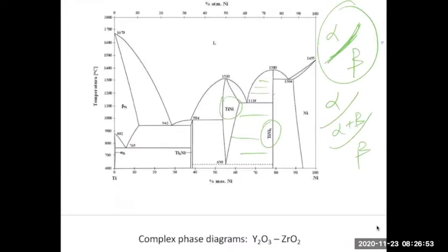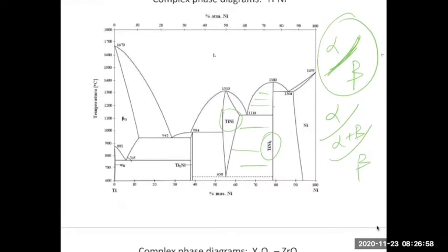Okay, here's a good example. Titanium. So titanium at low temperature, the alpha form of titanium is HCP. And then the high temperature form of titanium, the beta form, is BCC. So this is a classic vibrational entropy driven transition. You may wonder why are there all these polymorphic transitions? It's because the ground state energy of HCP and BCC titanium is close. It's close enough that at high temperature, the fact that BCC is slightly softer and has higher entropy can make it appear.